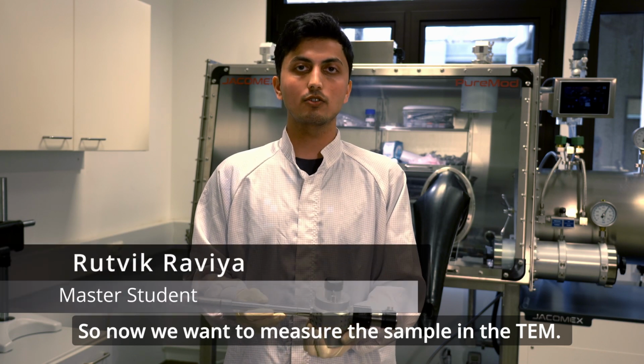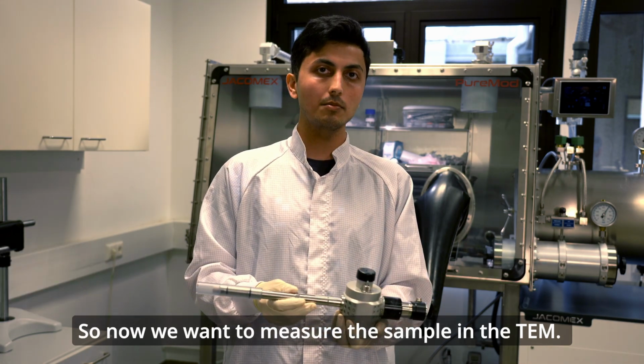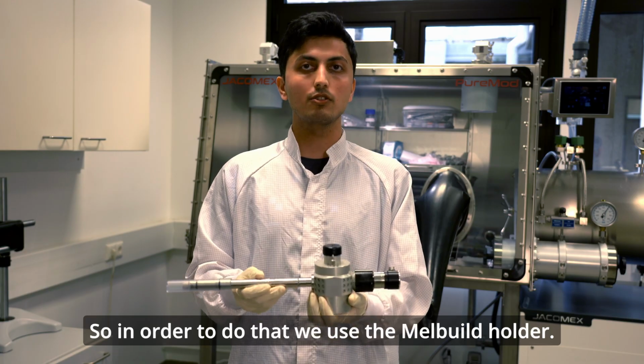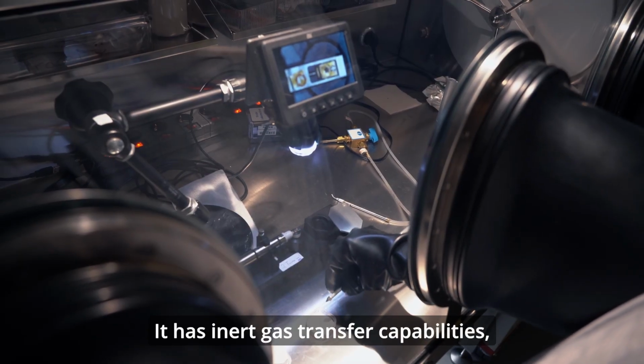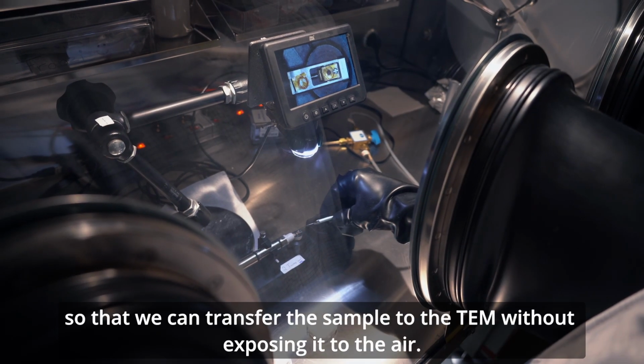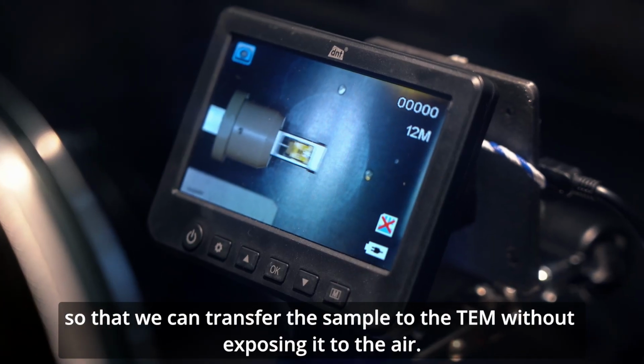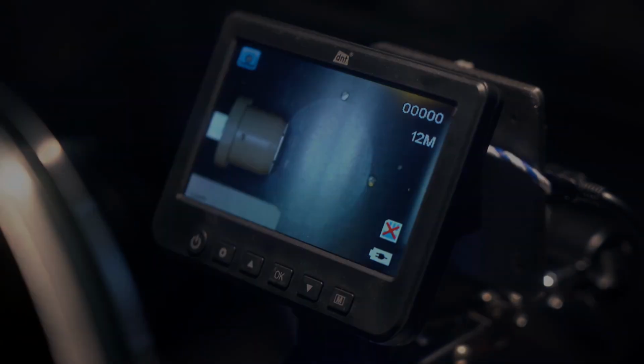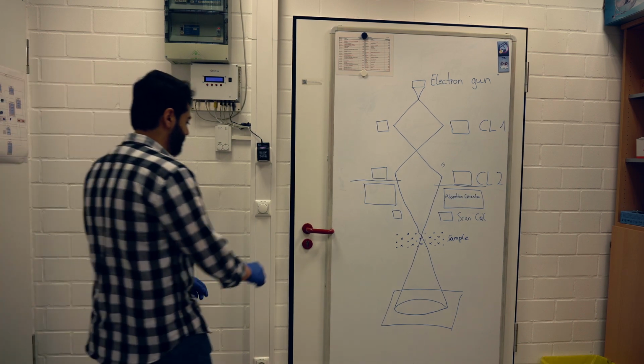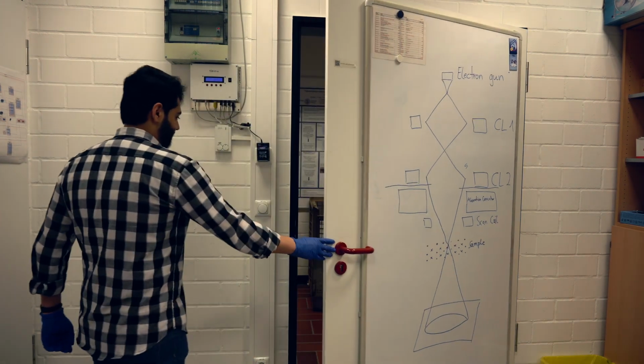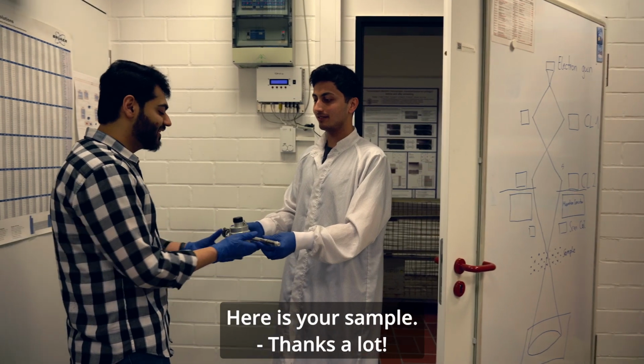So now we want to measure the sample in the TEM. In order to do that, we use the vacuum transfer holder. It has enough gas transfer capabilities so that we can transfer the sample to the TEM without exposing it to the air. Here's the sample. Thanks a lot.